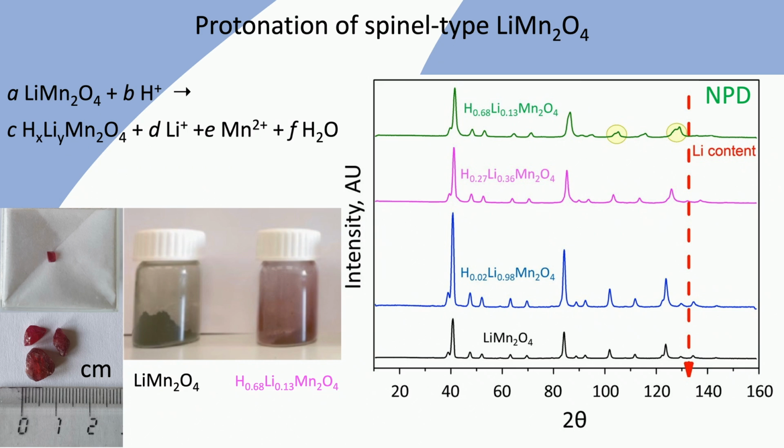As said, modeling also gives the fine structure of the crystal. For this material, it turns out that protons do not go to the position where the lithium ions have been removed. In crystallography, that position is called the 8a position, and it's a tetrahedron created by 4 oxygen ions. The lithium ion is then exactly in the center of the tetrahedron.